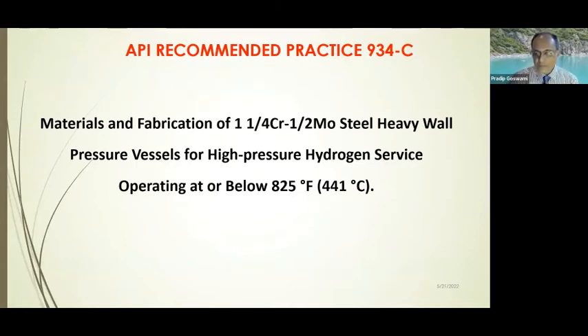Yeah. Okay. The next one is on API 934C. API 934C is typically the recommended practice for materials and fabrication of 1¼ chrome, half moly, heavy wall pressure vessels for high pressure hydrogen service. And typically these vessels operate at a temperature below 440 degrees centigrade or 441 degrees centigrade or 825 degrees Fahrenheit.